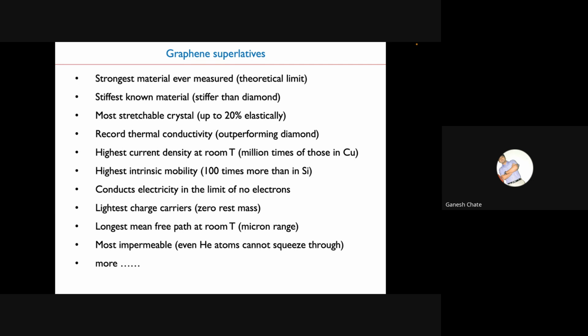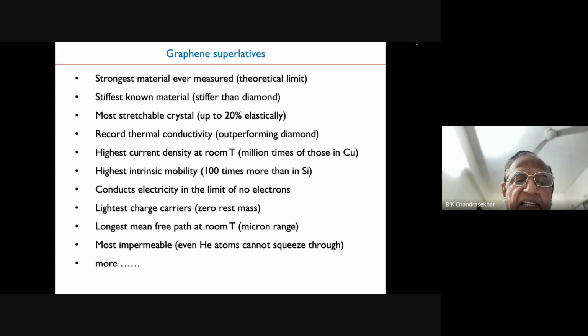Thermal stability of graphene - I think it's a very stable material. Nothing happens to graphene even at elevated temperatures, and it has one of the highest thermal conductivities, much better than diamond. If I remember correctly, copper has a thermal conductivity of 400 watts per meter Kelvin, while diamond has 2000 watts per meter Kelvin - meaning diamond is 5 times more thermally conductive than copper. Graphene is even better than diamond. Its stability is very good, at least up to about 500-600 degrees centigrade in an oxidizing atmosphere. In a non-oxidizing atmosphere, it's probably stable even at much higher temperatures.